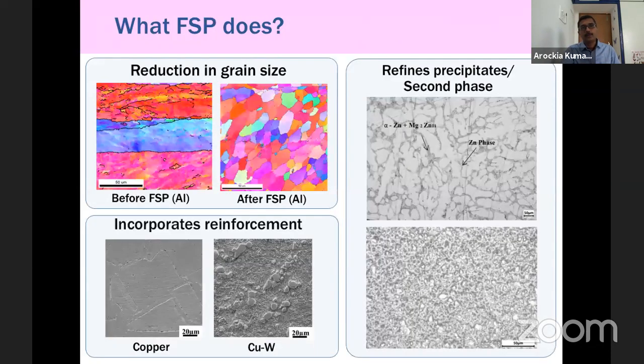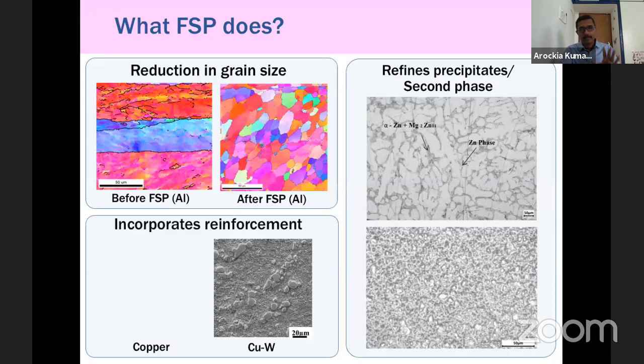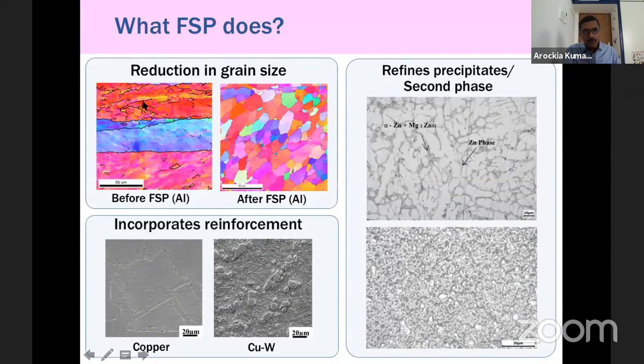So here, in my earlier slide I had just given it in terms of words, but here I am showing you in terms of microstructures. What I'm showing here are EBSD maps of pure aluminum before and after FSP. Before FSP, you hardly see maybe 3 to 4 grains. But after FSP, you are seeing several grains. So in this case, the grain size is reduced after doing FSP.